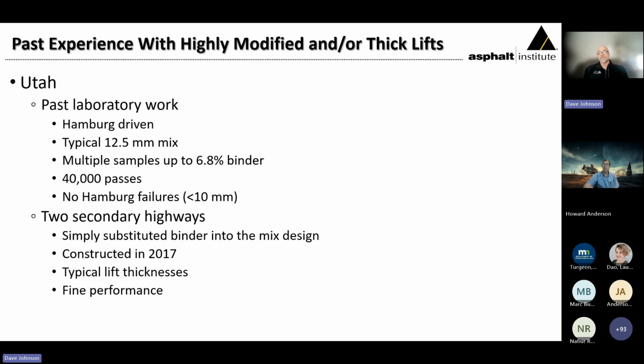They did a simple substitution on a couple of projects that were constructed in 2017. Well, the simple substitution was taking a Superpave mix design that had been designed with, I believe, a 64-34 binder, and they simply dropped in a 76-34 binder and laid it at typical lift thicknesses of around 2 inches. The performance on that has been very acceptable, but Howard recognized that we could get more out of this mix if we were willing to look outside of our normal box of volumetrics.